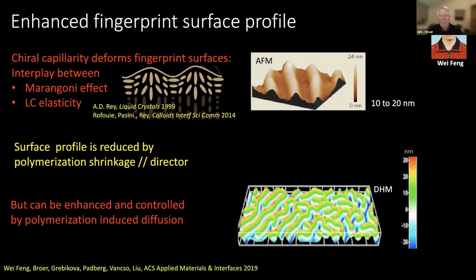One step further is that we can also control the initial surface structure. So I already argued at the beginning that the chiral capillarity deforms the fingerprint surfaces, and that you have the Marangoni effect more or less in equilibrium with the liquid crystal elasticity in the system that creates the surface roughness in these films. Of course, if you start polymerizing, the surface roughness is actually decreasing a little bit because the liquid crystal tends to have polymerization shrinkage, and the polymerization shrinkage is somewhat larger parallel to the molecular orientation than perpendicular to the molecular orientation.